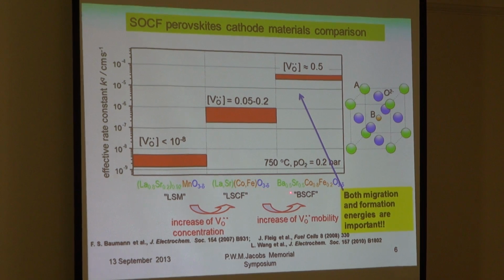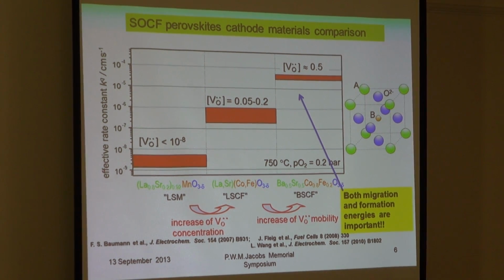If you replace lanthanum with barium in the same particular material, immediately you have an increase of the efficiency by another 2 orders of magnitude. In this case, the concentration of vacancies is comparable, but the difference is that now you have much more mobile vacancies. The migration energy is half of this, essentially. It's half an eV compared to 0.9 eV, the typical migration energy in perovskite. So for materials such as BSCF, you have both very highly mobile and very high concentration of vacancies. And both are important for fast oxygen transport.